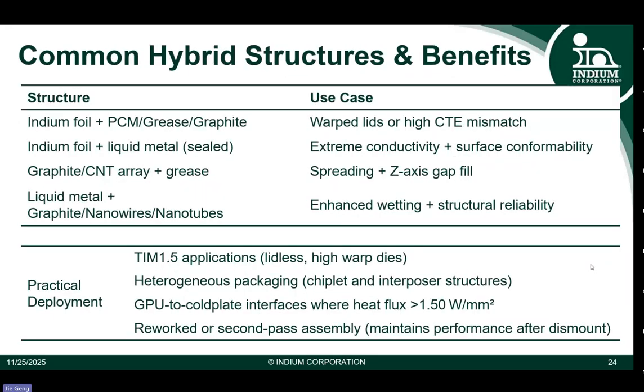So here shows the very common hybrid structures and their benefit. For example, the indium foils integrate with graphite or thermal grease, or sometimes even liquid metal. And also the graphite and the carbon nanotube can integrate with thermal grease, and liquid metal can be used as a matrix or a thinner to the nanowires, nanotubes, and also graphites. So both are adding the different types of TIM together to achieve the balance of thermal performance and mechanical compliance.